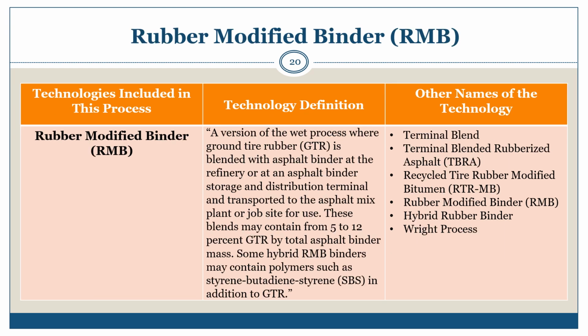Rubber modified binder, or RMB, is defined as a version of the wet process where ground tire rubber is blended with asphalt binder at the refinery or at the asphalt binder storage and distribution terminal and transported to the asphalt mix plant or job site for use. These blends may contain from 5 to 12% GTR by total asphalt binder mass. Some hybrid RMB binders may contain polymers such as styrene butadiene styrene, SBS, in addition to GTR.